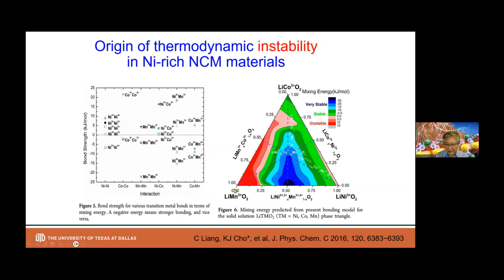The ternary phase diagram is reading pure lithium cobalt oxide, pure lithium nickel oxide, pure lithium manganese oxide. This color map shows relative stability compared to isolated, phase separated. So, for example, if you look at this data point, one third, it shows about minus 20 kilojoule per mole.